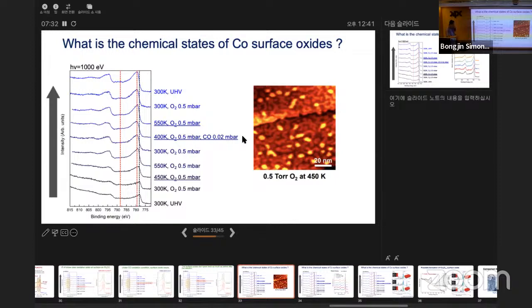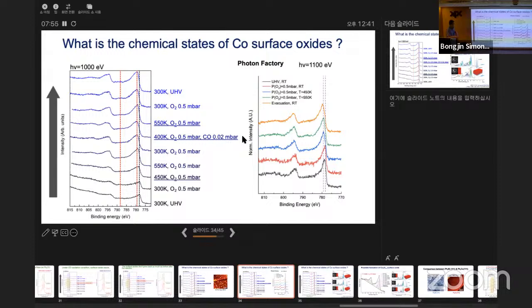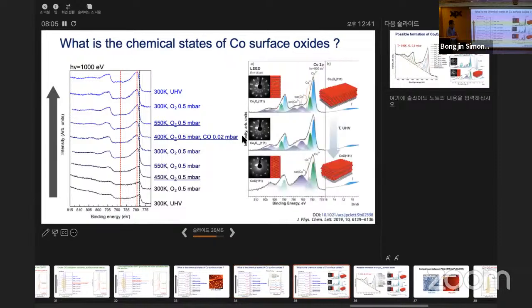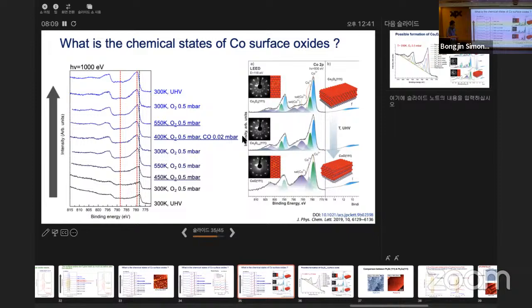And what about cobalt? Previously, I said in the case of platinum-3 nickel, I have a platinum nickel interfacial oxide. But what about cobalt? Can we identify a little further so that we could model the system? It turns out it's not easy, because in the case of platinum cobalt, the chemical state that you can see from the 2p level is not really distinct. We looked for references, and this is by far probably the best reference that we could compare. They grew the cobalt oxide on the surface of, I think, a platinum substrate. They deposited cobalt and grew the oxide, confirmed the chemical state, measured the cobalt 2p, and were able to fit the data.